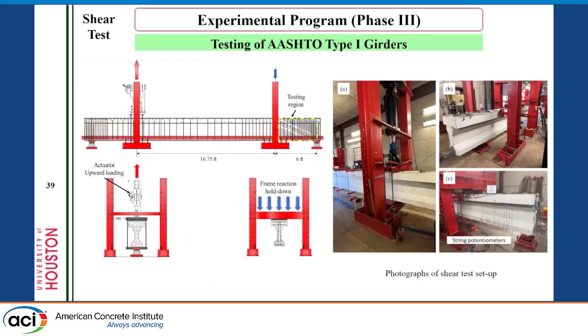This is for the shear test. We also tried to use some stainless steel stirrups. This is just the test setup, where because of the limits of our lab, the capacity of the actuator is just 230 kips, but we wanted 300 kips, so we switched it a little bit. Instead of going down, we went up here and made a reaction frame. So we applied only 100 kips here, and we got 300 there. That's just for the test setup.